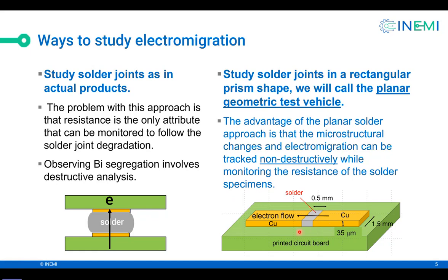And also, these specimens are very easy to fabricate. So we can fabricate a dozen of these in a day in an ordinary metallurgical laboratory. And the surface of the solder is highly polished, so it's like a metallographic sample. We can actually observe the microstructure, and I'll show you that in subsequent slides.